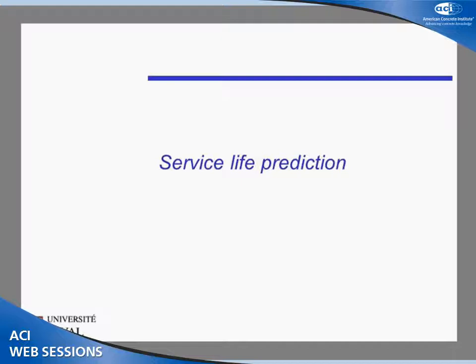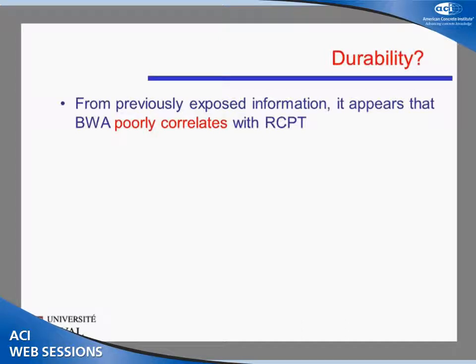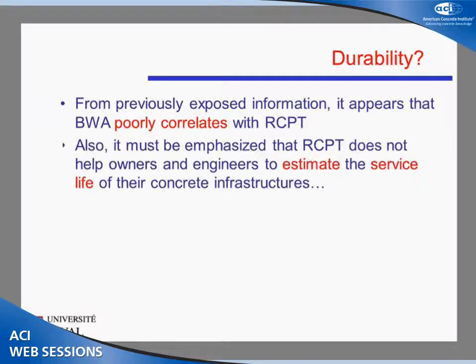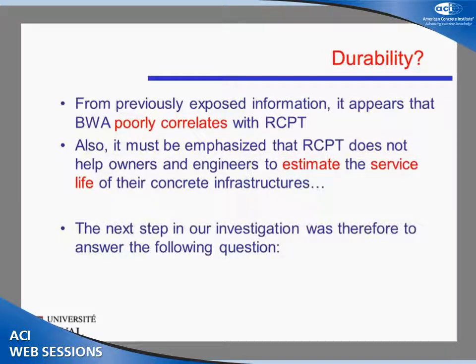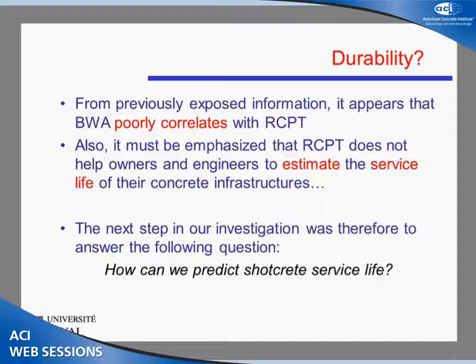So this brings us to the part where we talk about service life prediction. What we just saw from the results from phase one is that the boiled water absorption poorly correlates with the rapid chloride penetration tests. And it is also to be noted that RCPT does not necessarily help owners and engineers to estimate the service life of their structures. It gives you coulomb results of the RCP test, but it doesn't necessarily tell you how many years you can expect your structure to remain in acceptable condition. So the next step in our investigation was to answer the following question: how can we predict service life of Shotcrete?